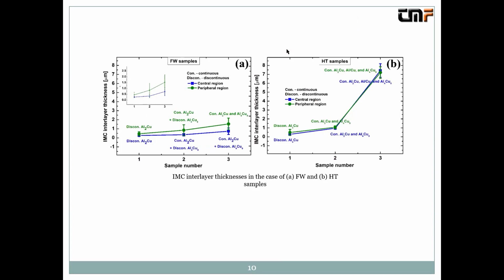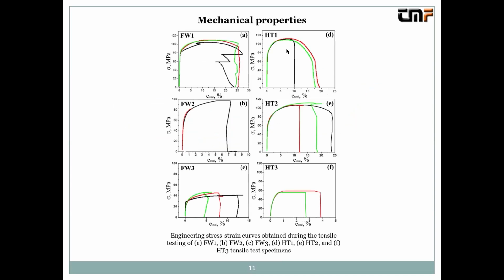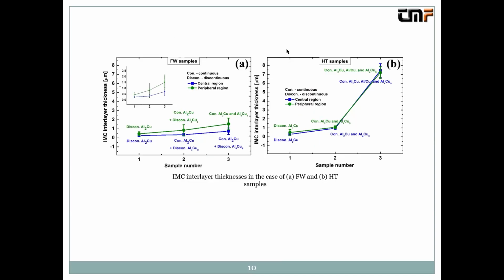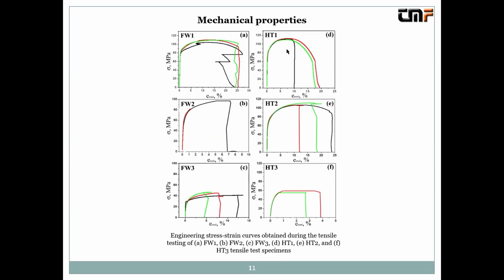So as I said, during the simulation, during the heat treatment and the welding, we obtained similar intermetallic composition in welded and heat treated samples, but there are some differences in the central region and peripheral region. The thickness of the intermetallic layer in the peripheral region was higher than in the central region. Mechanical properties showed slightly different results than we expected.